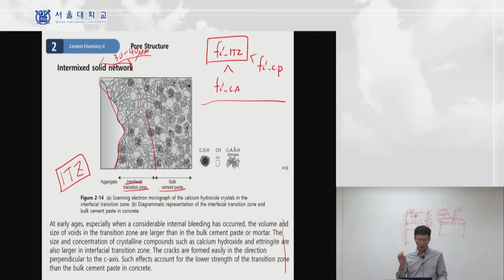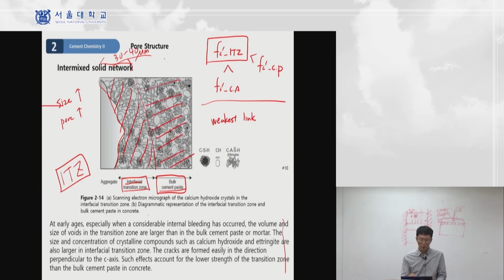So anyway, why do we have the weakest link surrounding the coarse aggregate? Because of the ITZ. Then why does the ITZ have weaker strength? Because we can see the size of crystals at that transition zone. In this transition zone, the size of crystal is large, and pores are also large. So basically there's more room or more space for hydration reaction at that specific region, and there's less formation of calcium silicate hydrate. If you compare the interfacial transition zone and the bulk cement paste, we can see there's less formation of calcium silicate hydrate in this region. There's just less calcium silicate hydrate, right?